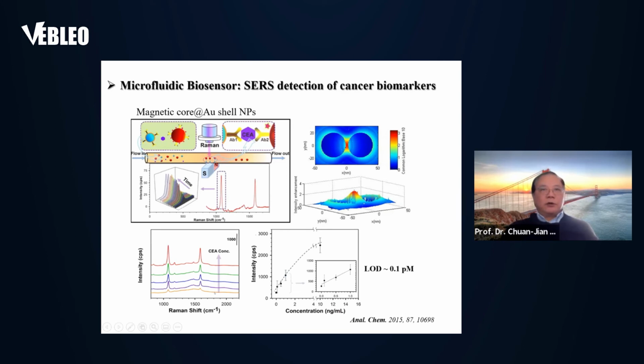Here's one example. You basically want to detect CEA. CEA is a cancer biomarker. You increase the concentration, you see the signal increase, and you plot the data, and then you can actually identify the detection limit. In this particular example, the detection limit is about 0.1 picomolar. That's not the lowest one. The lowest can go to femtomolar. We recently have data, but we have not published that yet. So that's really the direction we're heading to.